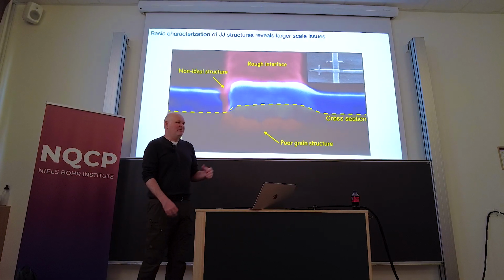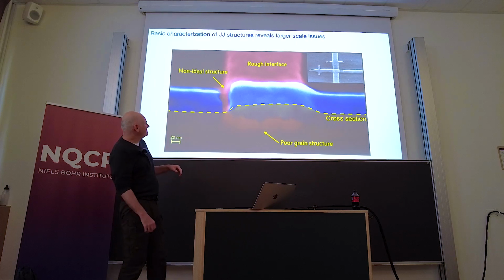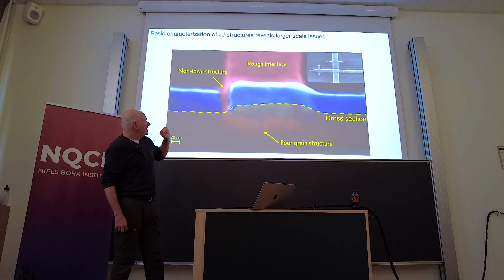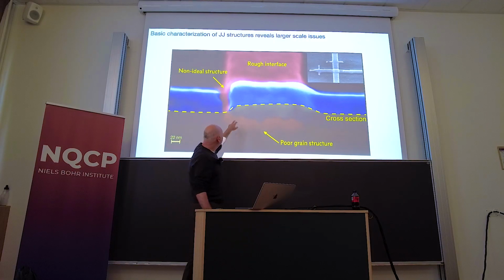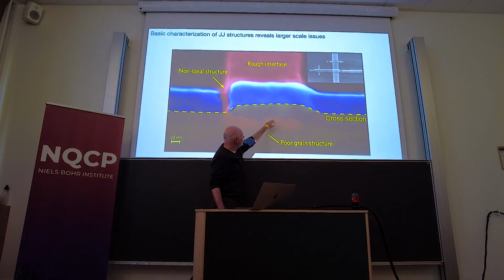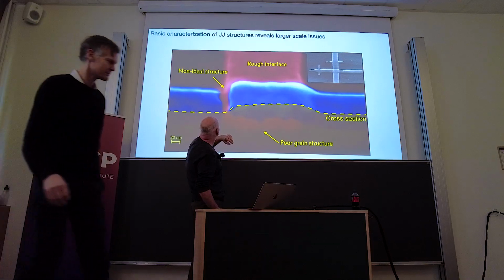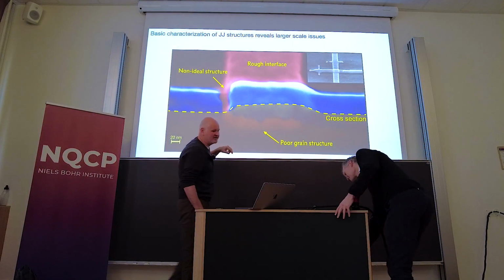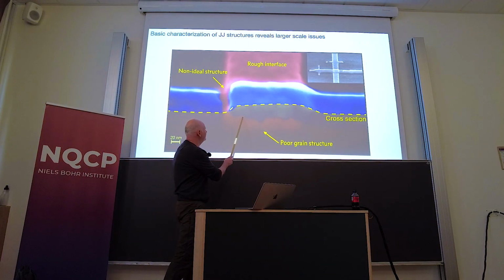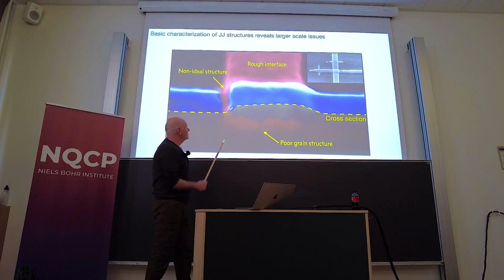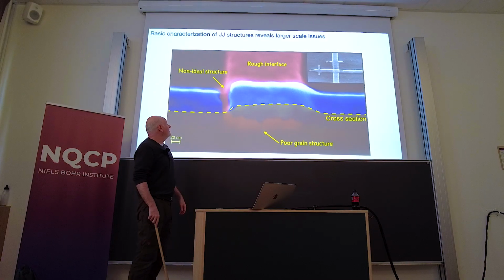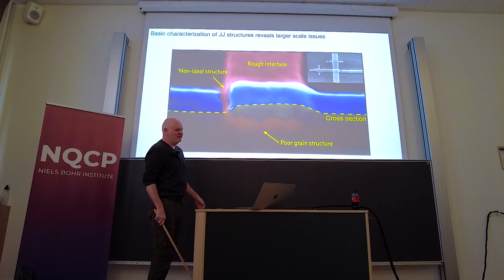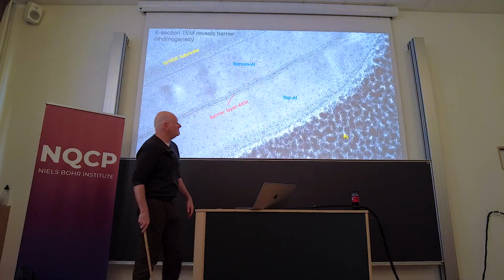And as you might expect, it doesn't look very nice. And I'm sorry, it's a little hard to see on the screen. But this right here is actually the interface between the two layers, between the two layers of aluminum. So aluminum, aluminum oxide, aluminum, the junction is here, and you can see it's very rough. The grain structure of the aluminum is poor. Also, there's non-idealities. And when you look closer with TEM, it gets even weirder.